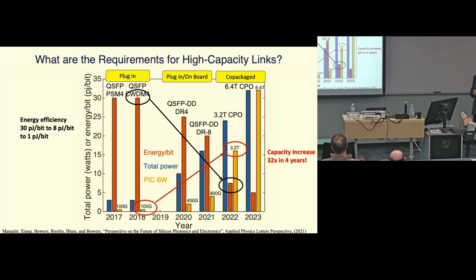So again, even so, we're talking about many kilowatts of power out of just one of these packages. And so it requires water cooling, so everything now is water cooled, and that's actually really good for lasers and really good for silicon photonics. Lasers obviously don't work well at high temperatures, and everyone's always complained that you can't have the laser in that package because it's way too hot. Well, now that you've got this liquid cooling there, and in fact, the liquid cooling goes directly on top of the PIC, that means the laser is actually fairly temperature stable.